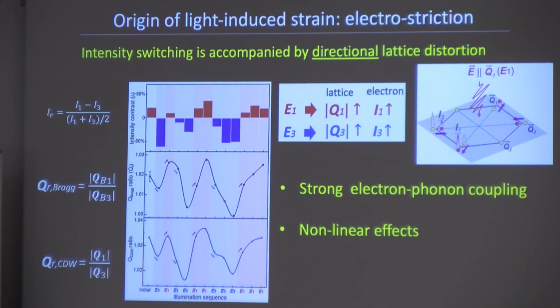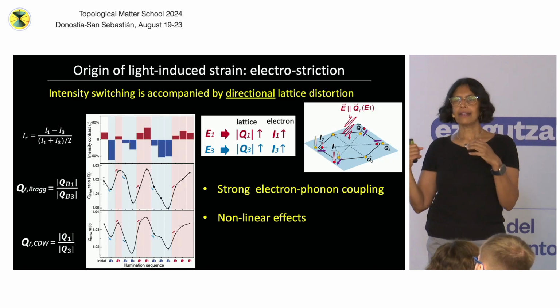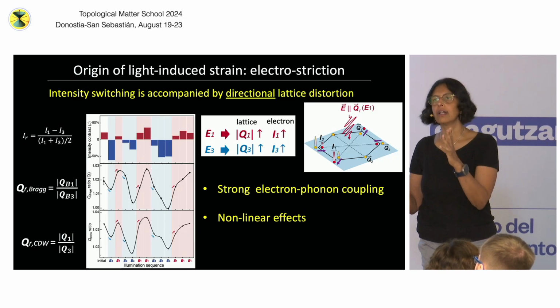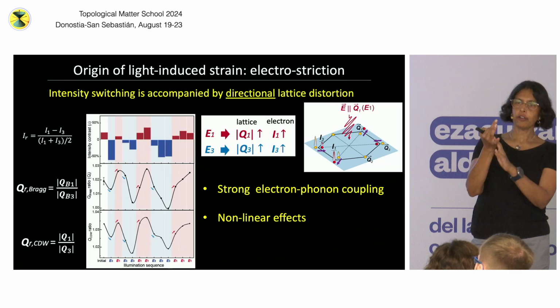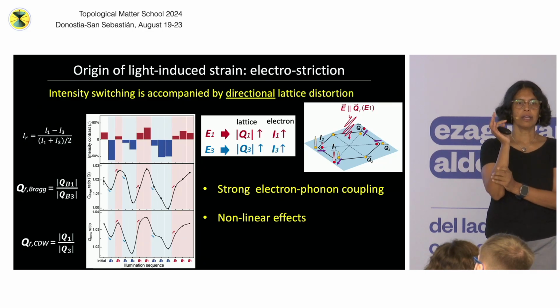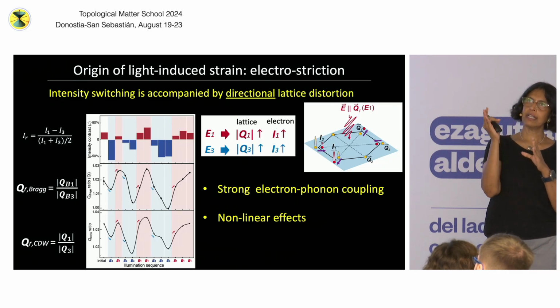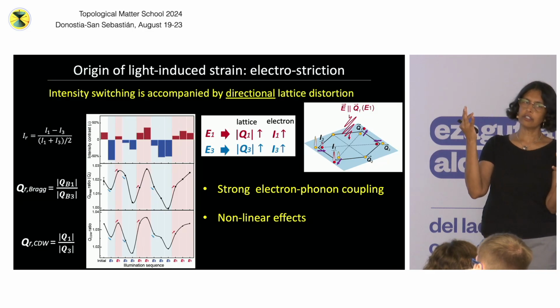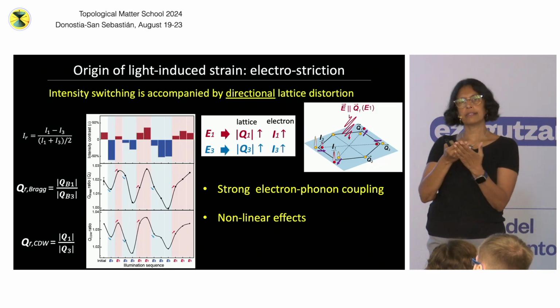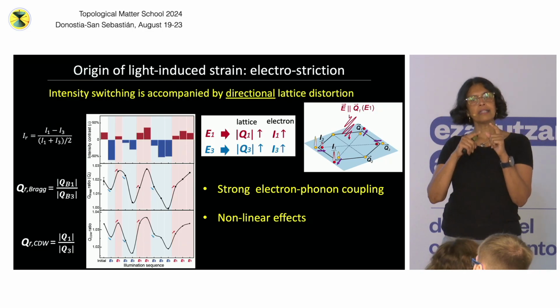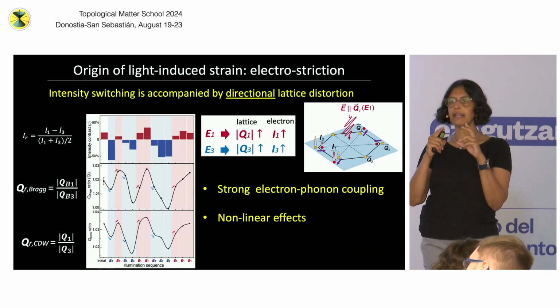So what the light experiments tell you is that A, of course, there's strong electron-phonon coupling. This could not have been possible without that. B, the fact that we're able to manipulate the charge density wave intensity with light means that the intensity of the CDW is a real measure of the order parameter, the relative intensity, okay? The intensity of the CDW by itself, if you didn't do anything to it, you actually don't know what's going on. You don't know what's determining the intensity. However, the relative intensities of the different peaks have physical meaning, okay?